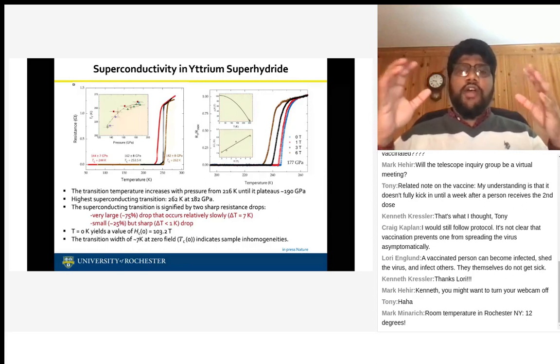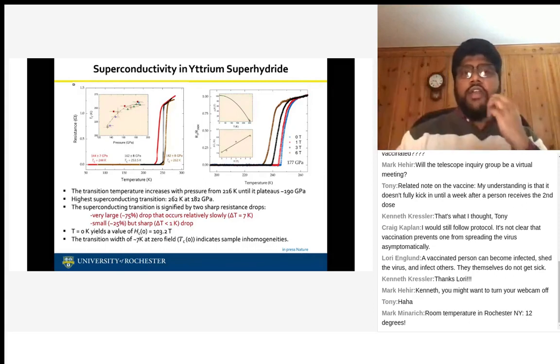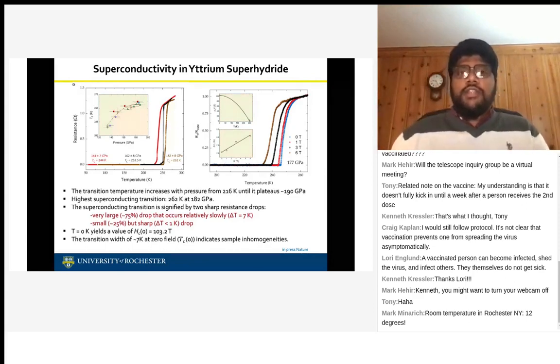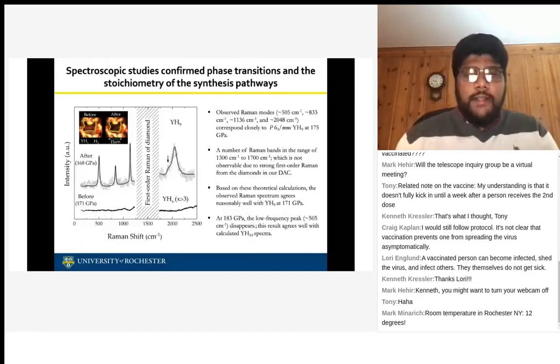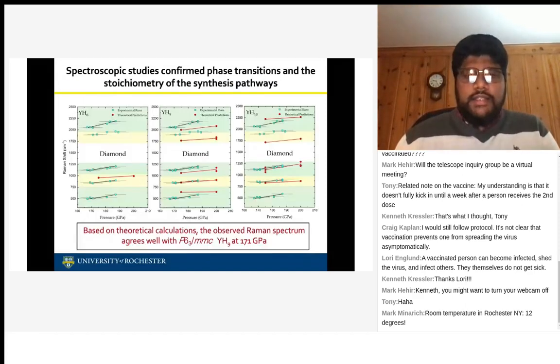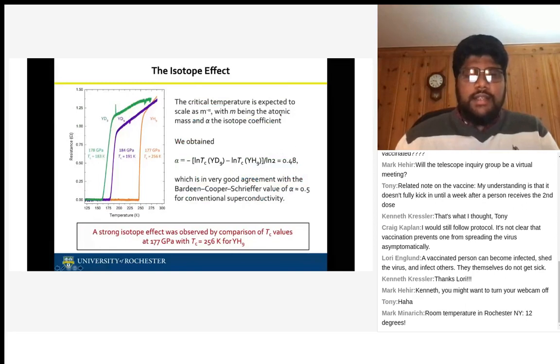So then you will see that your transition temperature is definitely affected. It should reduce to a lower temperature. So with that, we observe that if you look at this graph right here, this is the temperature and this is the resistance. And you see that this is YD9, replaced with the deuterium. You cool it down, your resistance goes down and down, and all of a sudden it disappears and goes to zero.